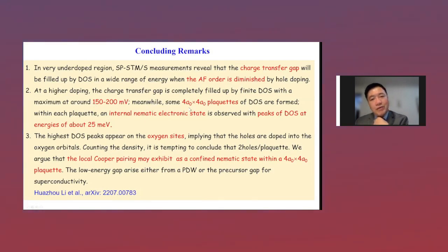Meanwhile, some 4a by 4a plaquettes of density of states are formed. Within each plaquette, an internal nematic state is observed with peaks of density of states at the low energies. The highest density of states peaks appear on the oxygen sites, implying that the holes are doped into the oxygen orbitals. Counting the density, it is tempting to conclude that there seem to be 2 holes per plaquette. We argue that the local Cooper pairing may exhibit as a confined nematic state within a 4a by 4a plaquette. The low energy gap arises either from a pair density wave or the precursor gap for superconductivity.